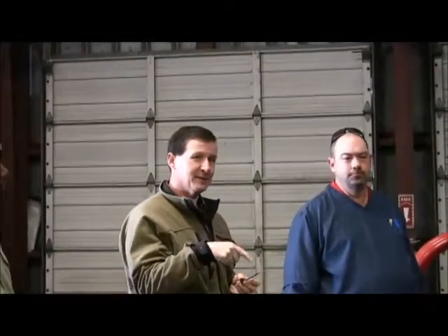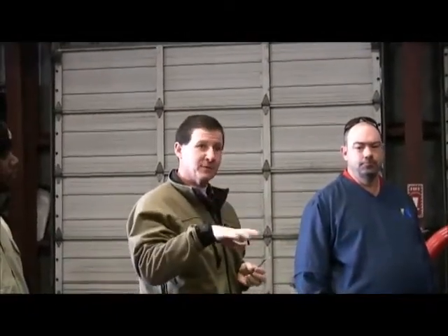Can I interrupt just a second? Sure. I noticed one thing. You see how he drilled it a second time? He took a look at it, he drilled it a second time. He was looking for those clean cut edges. Just because you run it through a few times is fine, but look for that clean cut steel. He did it real slow again just to clean those last few. I bet you had some loose edges right on this inside. It didn't look like a smooth hole, that's why I hit it again. Clean, tight hole is what you're looking for. Nothing loose, nothing frayed.